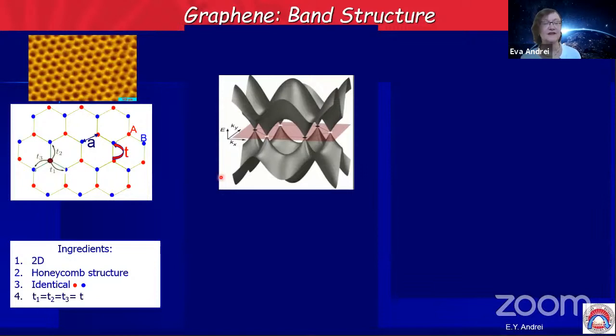So let's see what causes this strange band structure. In fact, there are only 4 ingredients that go into this band structure. Number 1 is the fact that we're 2-dimensional. This is critical. Number 2 is the fact that we have a honeycomb structure, which is not Bravais. Number 3 is that we have identical atoms. We have carbons. Both the red and blue sites are filled with carbon atoms. And lastly, the hopping integral, the probability of hopping between the red and the blue site, is the same in all directions. So these ingredients are what give us this strange band structure.